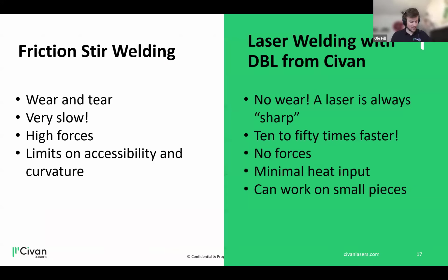So to sum up this topic of aluminum die-cast welding with a Civan laser, where I bring up a comparison to a competitive welding technique that is friction stir welding. If you're not familiar with it, you basically use a pin, you apply a lot of force, and you work below the melting temperature. You're just mixing the two joining partners. You're not really melting them.